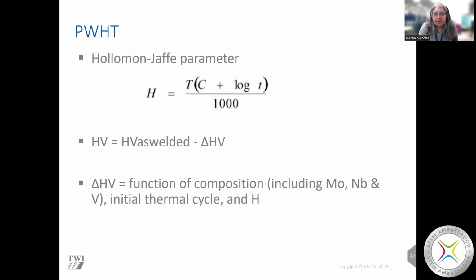The Holloman-Jaffe parameter gives me a value of H, which is the temperature multiplied by a constant plus the logarithm of the time, all divided by 1,000. And the hardness is the as welded hardness minus a change in hardness. And that change in hardness, delta HV, depends on the composition and the Holloman-Jaffe parameter. So that works for post-weld heat treatment, but it can also work for the weld thermal cycle.